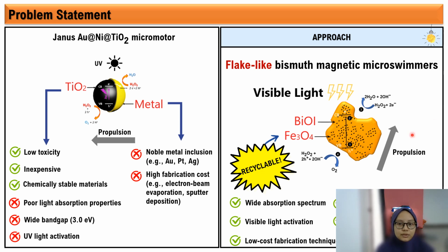The idea of this study is to induce the movement of the microswimmers through visible light activation and the asymmetric shapes of the microswimmers. Hence, bismuth oxyiodide is chosen since it has a wide absorption spectrum, a low band gap, and can be activated by visible light. Moreover, the asymmetric shape of the microswimmers itself excludes the coating of noble metal and can be produced using a simple hydrothermal method. Moreover, this study used magnetic nanoparticles as an additional magnetic property feature. Hence, it can be recycled.